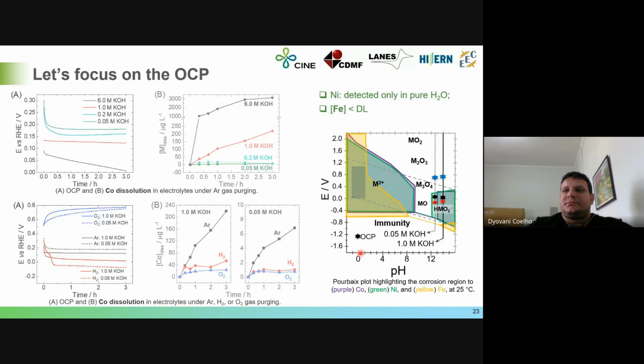And this happens because with the hydrogen purging, the potential of the electrode is kept lower than the thermodynamic potential for the hydrogen evolution reaction, which means that probably the purging with hydrogen keeps the environment reducing, to protect the metal from oxidation. And with oxygen, actually, the cell potential, as we can see here, is higher and produces high valence oxides, which means that the production of the high valence oxides can passivate the catalyst surface and protect the catalyst from further dissolution.